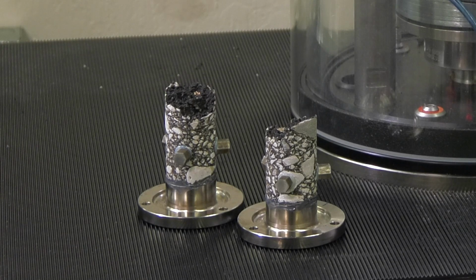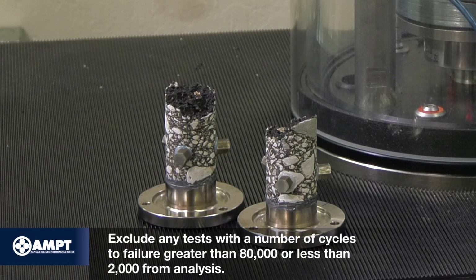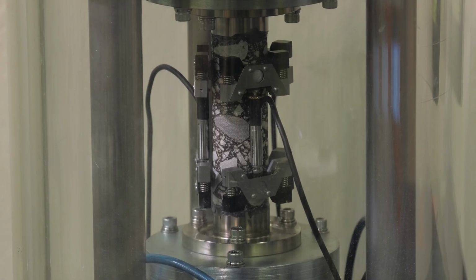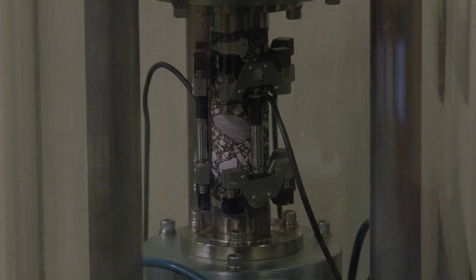Examine the crack pattern of the tested specimen. If the specimen breaks between the gauge points and end platen, the data should be discarded and the test repeated on a new specimen. Exclude any test with a number of cycles to failure greater than 80,000 or less than 2,000 from analysis. Repeat this process on the remaining test specimens.